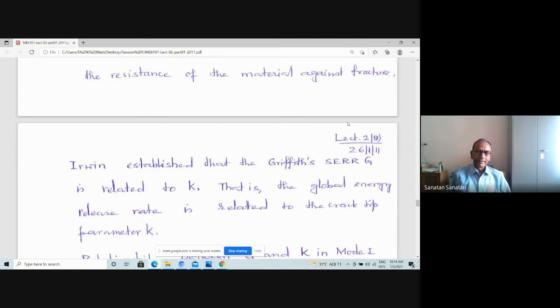So that's fine. But then people also found that the energy balance concept of Griffith is a very sound concept, and therefore you cannot just say that the stress intensity factor is the parameter which is leading to failure. It was very important to establish that this reaching of a critical value of K is also linked to the conditions that Griffith gave: that at the point of unstable crack extension, the energy release rate reaches a critical value, which is equal to the energy required for creation of new surfaces.